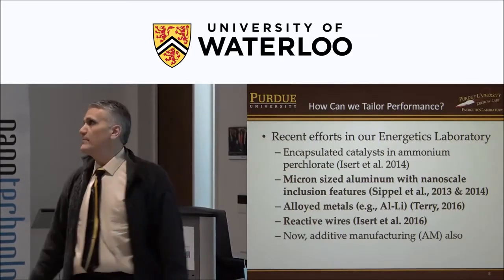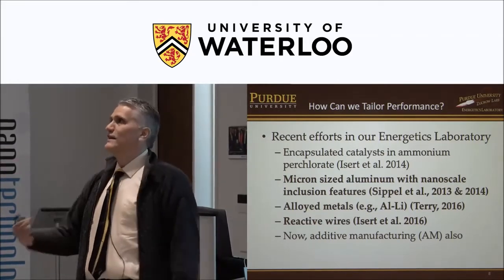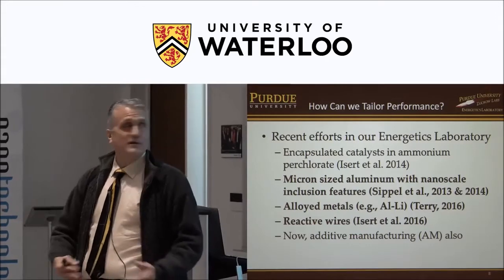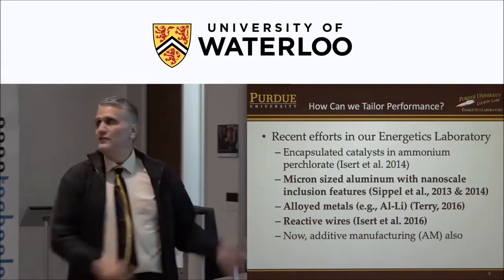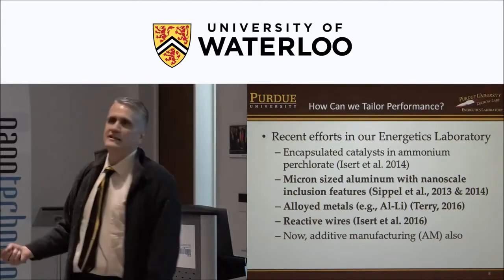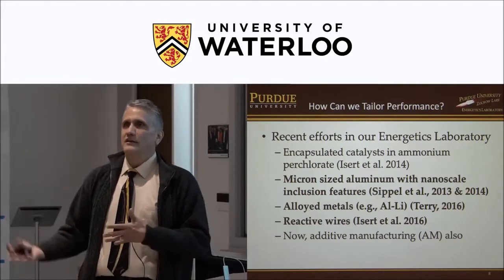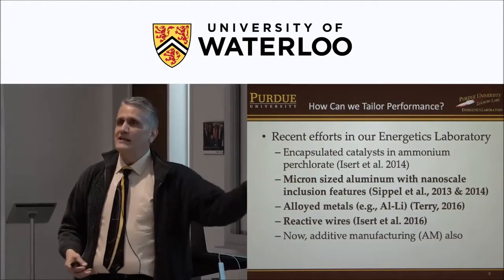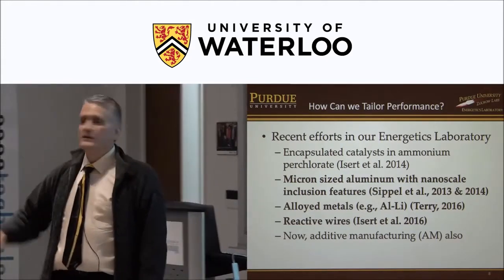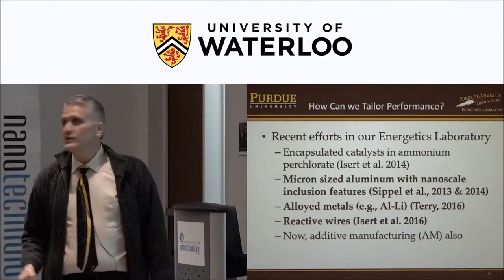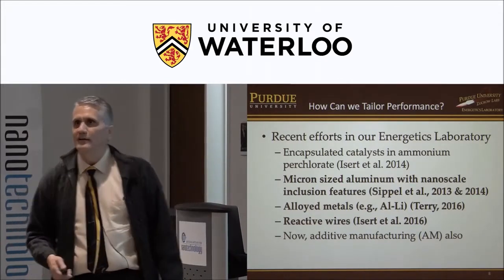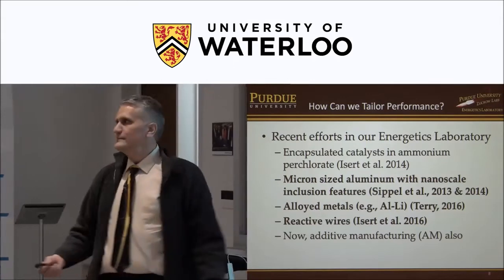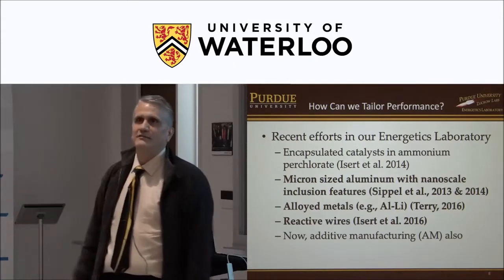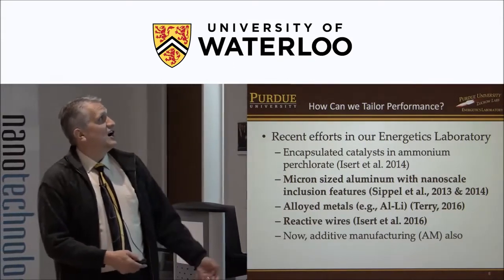It'd be nice to get rid of that, but people have looked at additives, and it kills performance. You're cutting the energy. The lithium, being halophilic, forms lithium chloride instead of lithium oxide. And so it ties up that chlorine, and you produce hydrogen instead without the HCl. So it's less toxic pollutants and less caustic.